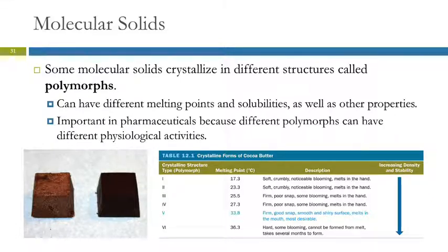As it cools down, the different crystalline structures begin to form. If you let it cool down all the way, you're going to have a mixture of them, and you're going to have low-quality chocolate. So they let it cool down a little bit, and then they heat it up again. So they cool it down so that at least some of this polymorph 5 has started to form. Then they warm it up again so that all of these lesser forms melt.